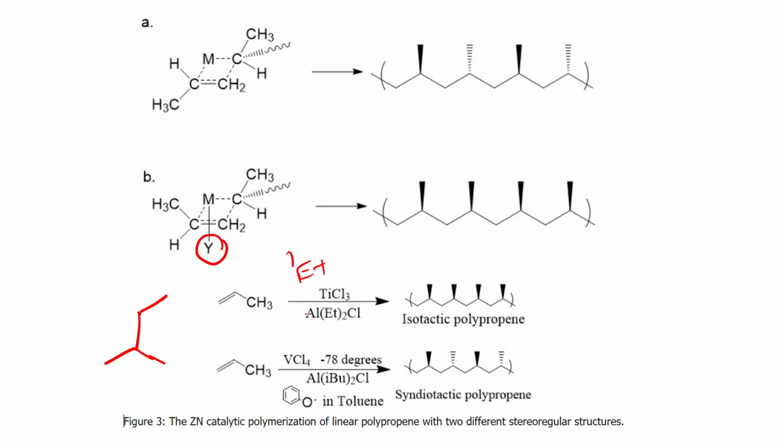So what happens is for this particular case, this methyl and this methyl interaction is much more prominent compared to your methyl-ethyl interaction. But when you have this bulky isobutyl group, this isobutyl and methyl repulsion predominates, and then the system tries to minimize that. And for this kind of case, this methyl-methyl interaction is much lesser compared to the methyl and isobutyl interaction. So that's why this particular orientation changes.